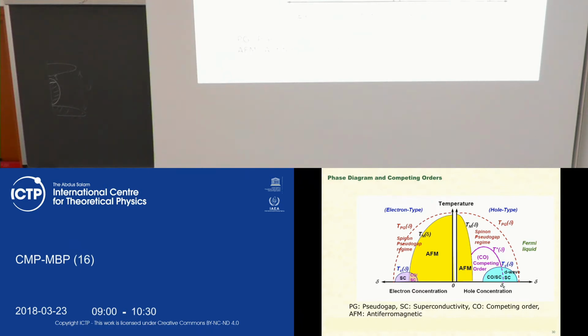There is a so-called pseudo-gap regime, where the gap in the electron spectrum, if seen by ARPES, is already visible, but phase coherence is not reached, so the system is not a superconductor. So this is more or less what people understand nowadays about the theory of high temperature superconductivity.